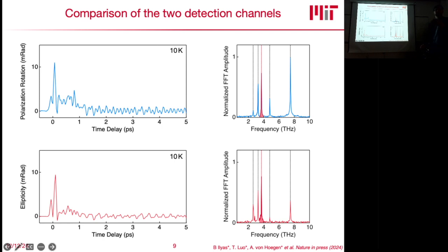Can I ask a question? Please, yeah. How long do you have to measure after the pump signal in order to have those very narrow lines? Good observation. So here I basically truncated and zoomed in on this region just after time 0, but we actually measured out to 150 picoseconds. So we measured for a pretty long time, and then we usually stop this delay scan at a point where we don't see these coherences anymore.